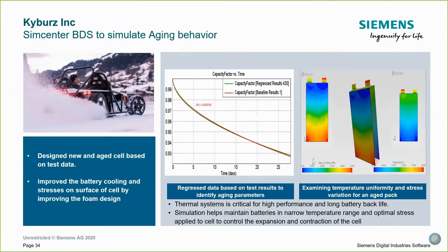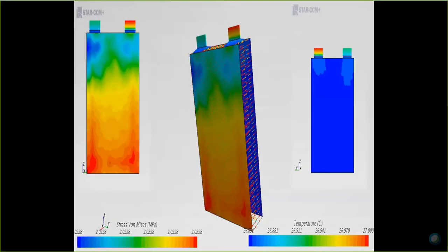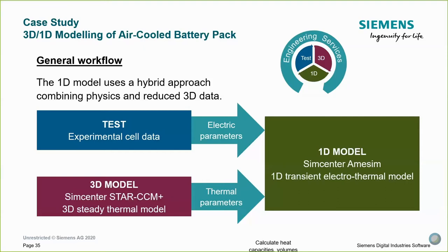What we could also do is simulate aging behavior, where we could use half of your cell data and use machine learning to predict the model, which accounts for varying depths of discharge, C rates, and temperatures, and then fit that on the other half. That's what we tried to do for this model. And what we noticed was the temperature rose almost 15 degrees higher in comparison, and the original capacity fell to 76% at the aged cell verification.